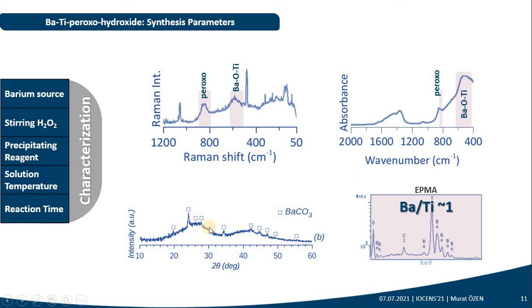In XRD, we'll be looking at a broad band, and also if there are unwanted or secondary phases. For example, in this particular XRD diffractogram, we see the unwanted barium carbonate phase. But what we want is a very broad diffractogram, such as here, without the barium carbonate. And in the elemental analysis results, we'll be looking at a barium-titanium ratio of about 1.